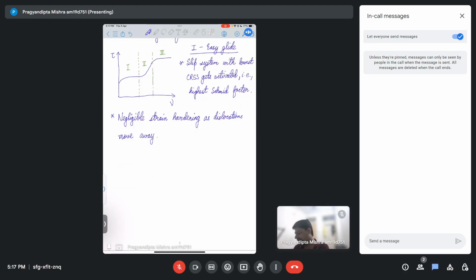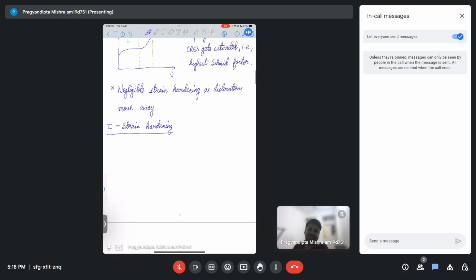So next step, where we'll see a sudden rise in the strength, is strain hardening. So this is the major step. So in the strain hardening step, now more than one slip system will become active. Okay, so once that happens, dislocations will start to interact with each other, and you will see almost linear strain hardening behavior. Essentially pile up of dislocations will happen. They will start interacting with each other, and they will tangle with each other and form some sort of a cell structure. So this will lead to strain hardening behavior. So that's why this stage is known as strain hardening.